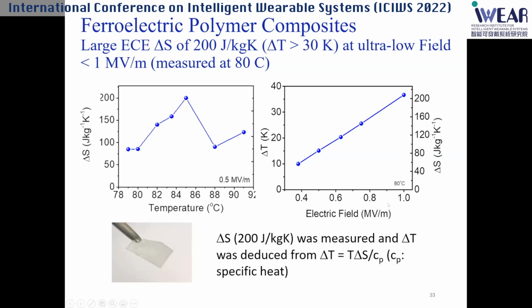This means just 1 volt per micron. So if you make a 5 micron polymer film, you can use just 5 volts to generate this electric field, and the temperature change can be more than 30 Kelvin. This is still not practical because it happens at 80 degrees C, so we still have quite a lot of work to do moving to room temperature. But this shows there's a lot of potential in polymer-based systems to generate large electrocaloric effect.